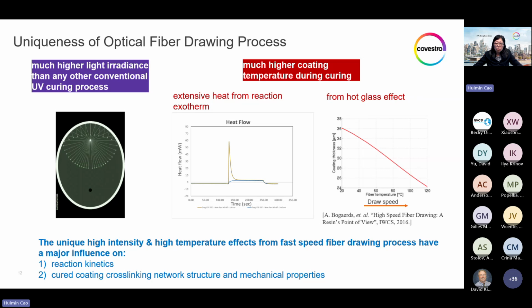We think this has a lot to do with the uniqueness of the optical fiber drawing process, with the processing window much faster than any other coating application. Fiber drawing draw towers are equipped with well-designed reflectors with the UV light highly focused on the tiny spot of fiber, which means much higher irradiance than any other coating applications. And the higher intensity light results in a very fast reaction, and the fast reaction creates extensive heat as exotherm. Plus, when the fiber drawing speed goes very, very high, the glass fiber becomes very, very hot. And the fiber temperature can easily go even above 100 degrees C, and that also contributes to the coating temperature during curing.